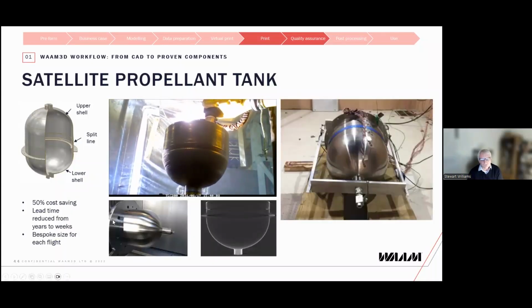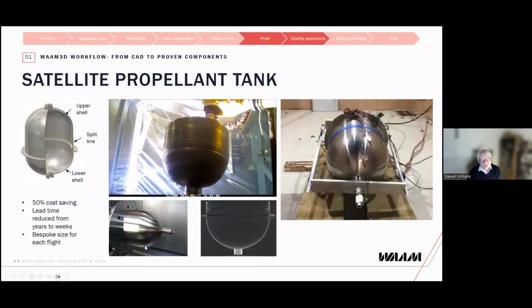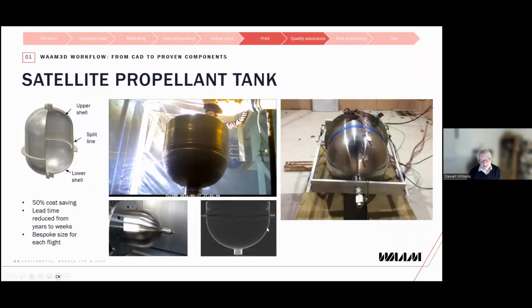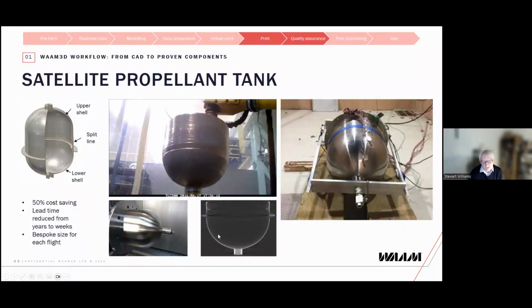So we then, of course, needed to test it. So we get it machined. This is an X-ray CT image, an X-ray image, sorry, of the part. There are no defects in it. It was then tested and compared to the forged part and performed identically, even as far as it was tested to failure, and the failure mode was identical to the forging. So this gives us a 50% cost saving, the lead time reduced from years to weeks, and we can have a specific size of tank for each flight instead of the predetermined ones based around tooling.